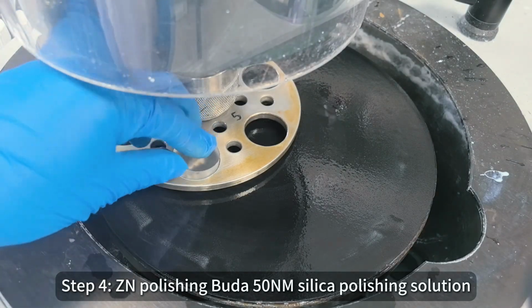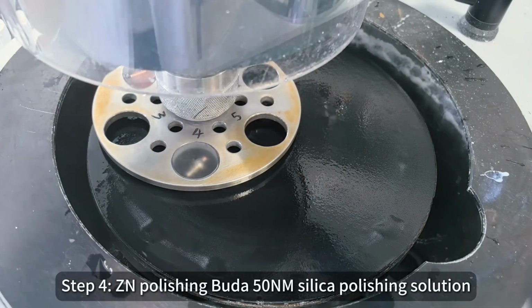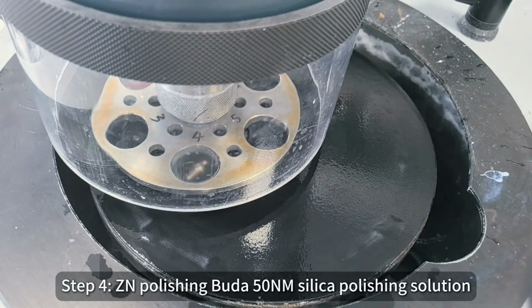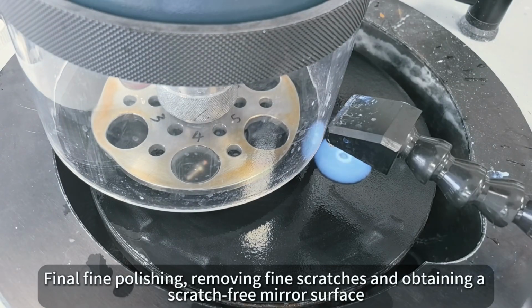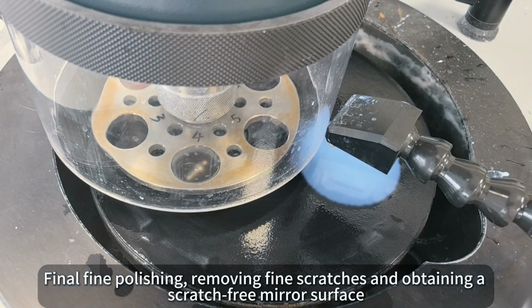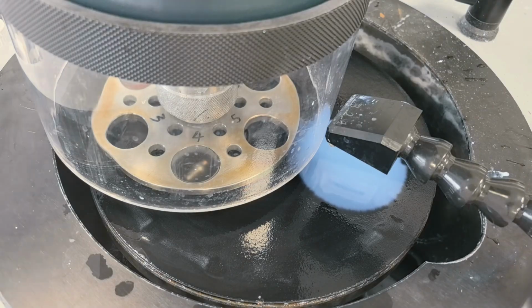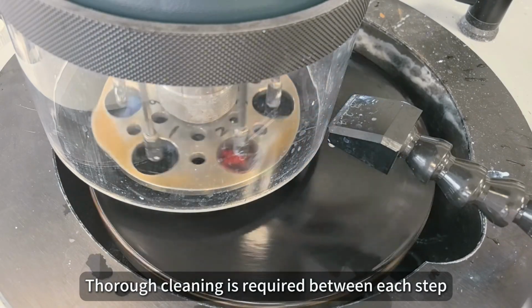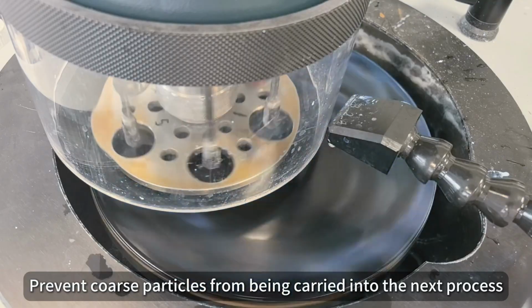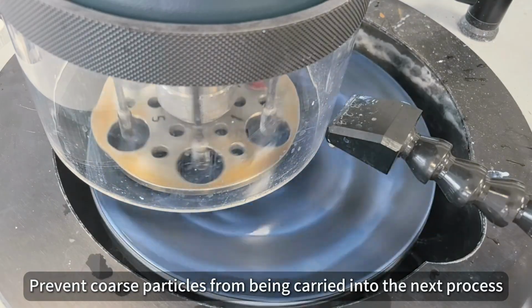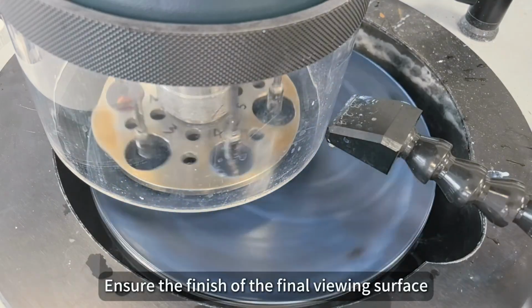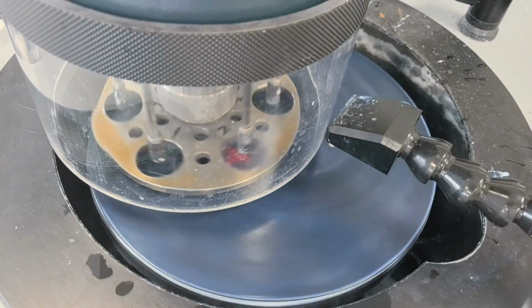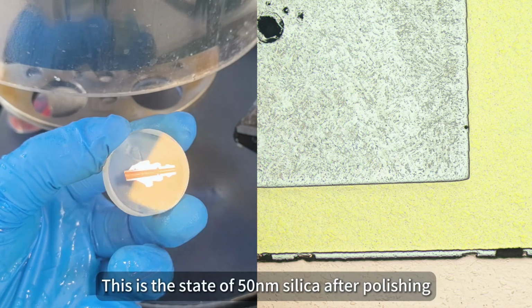Step 4. ZN polishing with Buehler 50nm silica polishing solution. Final fine polishing, removing fine scratches and obtaining a scratch-free mirror surface. Thorough cleaning is required between each step to prevent coarse particles from being carried into the next process and to ensure the finish of the final viewing surface. This is the state of the 50 nanometer silica after polishing.